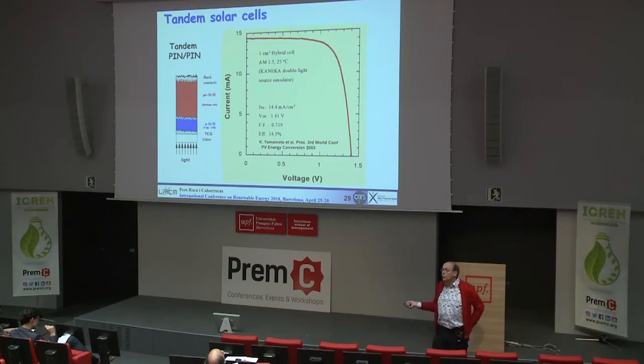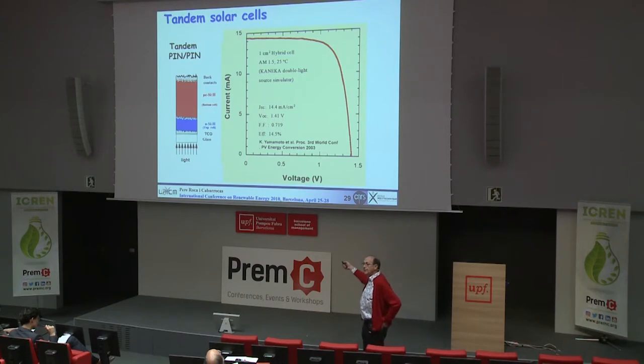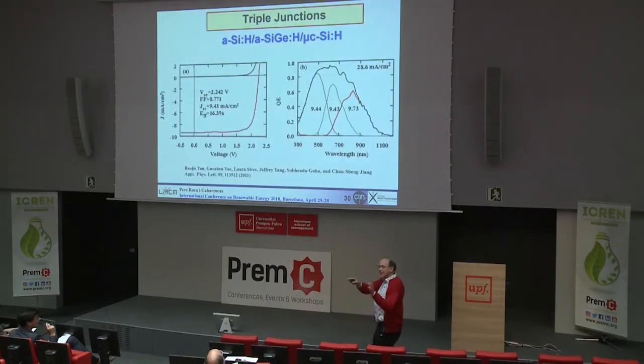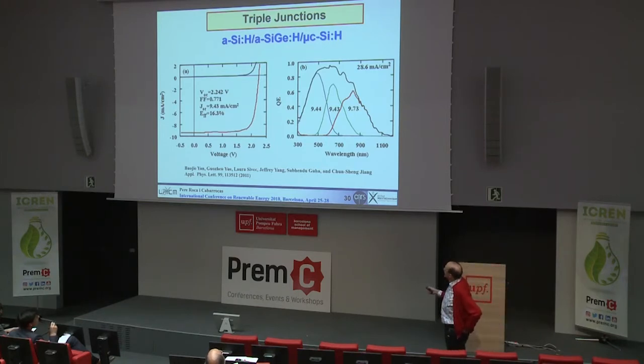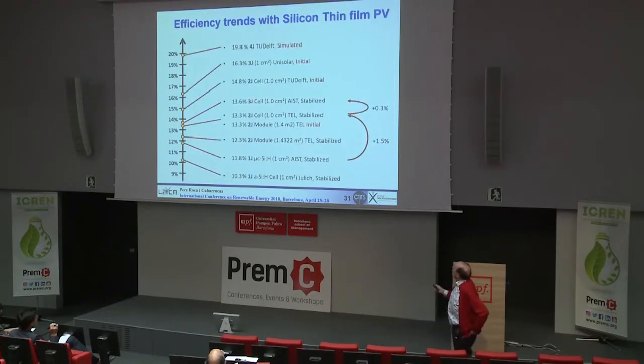If you can do tandem, why not do triple? Just put another PIN. Someone there is an expert on triple junctions. So triple junction, that's the record for the time being: amorphous silicon, silicon germanium, microcrystalline silicon. You see that you cover a wide range, and now you have efficiency 16.3, VOC, fill factor, whatever. But so we are getting efficiencies up. And if you look where we could go, 20% without any fundamental limitation using this technology. All this is amorphous, microcrystalline, not so perfect materials.